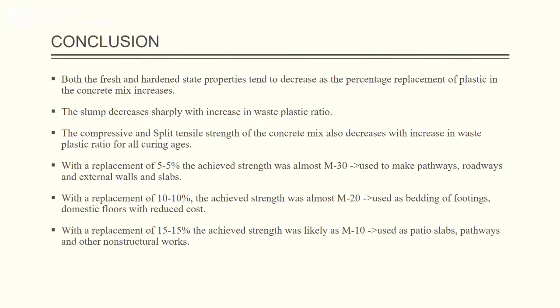With a replacement of 15%, the achieved strength was likely M10, which could be used as patio slabs, pathways and other non-structural works. With lesser density, the 10, 15 and 20% replaced specimens fall under the lightweight concrete category, hence decreasing the dead weight of the structure. The various civil engineering applications where it can be used are namely precast bricks, partition walls, panel walls, canal linings and so forth.